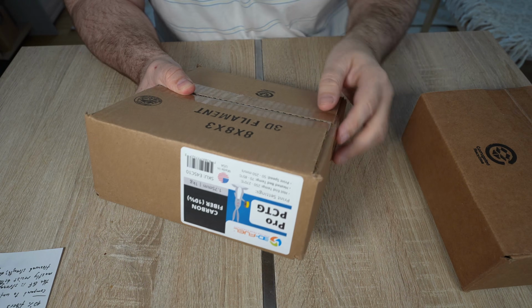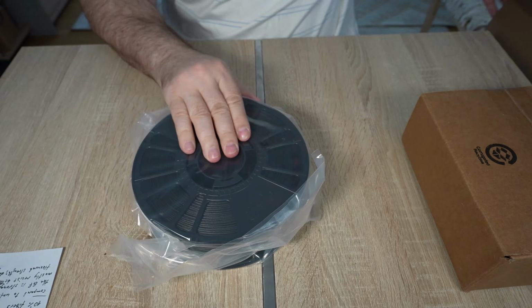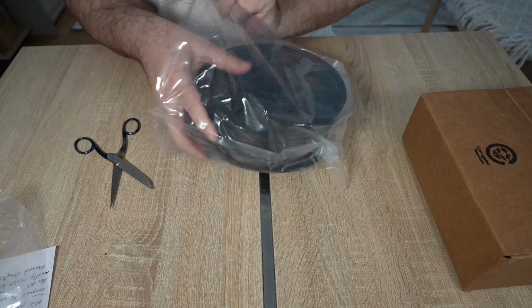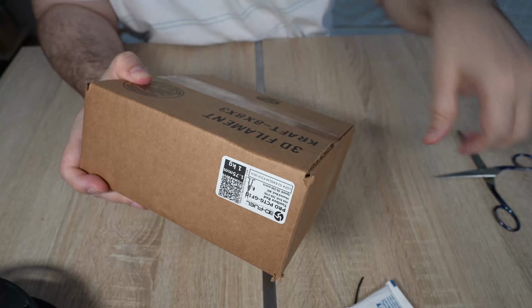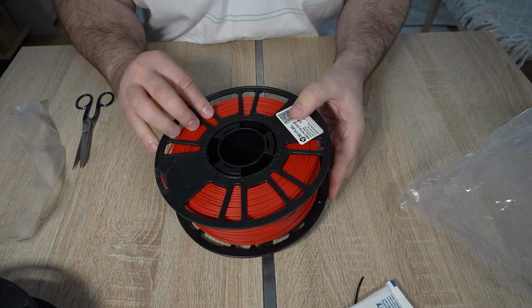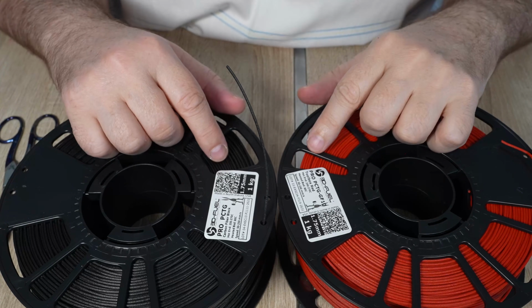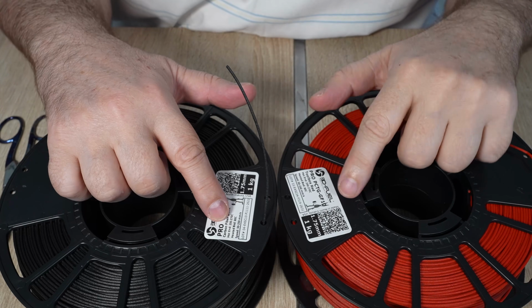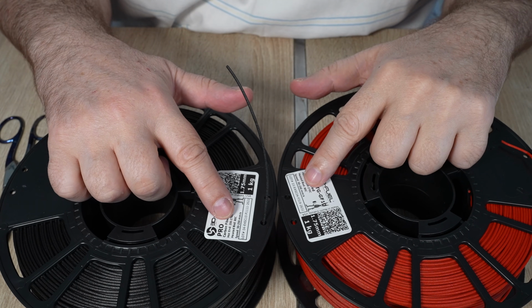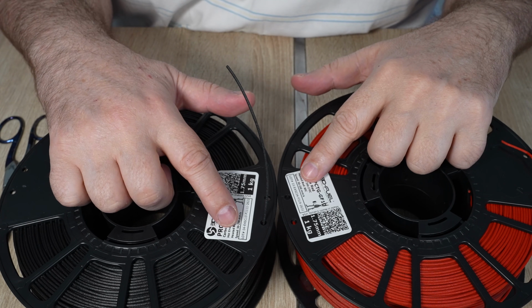This is the carbon fiber version. The second, glass fiber version. On the sticker similar information: the print temperature between 250 and 270 degrees Celsius, bed 80 degrees, and the speed between 50 and 250 millimeters per second.